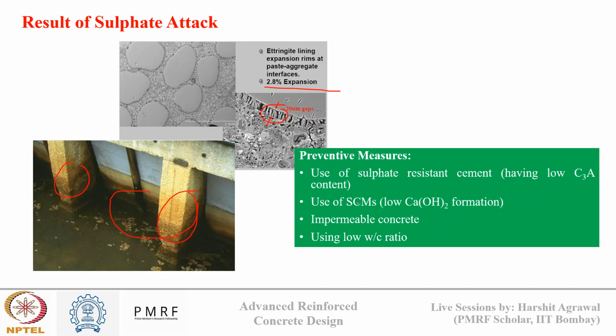And how to prevent this? We can prevent it by using sulfate resisting cement, which has low C3A content. If there is low C3A content, there will be less ettringite formation and less sulfate attack. We can use SCMs which consume CH and create a dense microstructure that will lower the ingress of sulfate ions. We can make concrete impermeable, which is what SCMs are doing, or we can reduce the W by C ratio also to make concrete impermeable, and these are some of the preventive measures for sulfate attack.